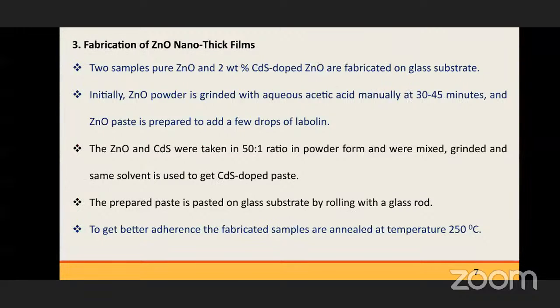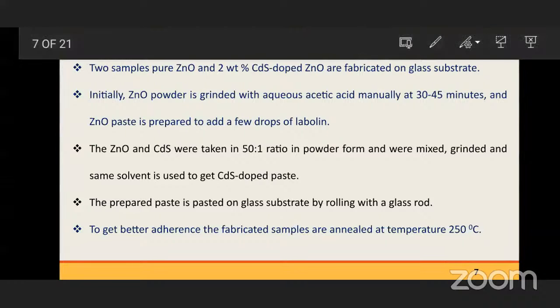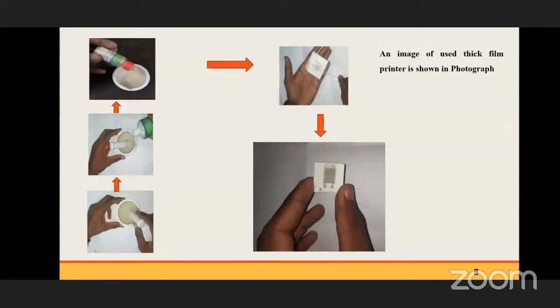Fabrication of ZnO nano thick film. Two samples, undoped ZnO and 2% CdS doped ZnO, are fabricated on a glass substrate. Initially, we take some amount of ZnO in a porcelain mortar and grind it for some time.